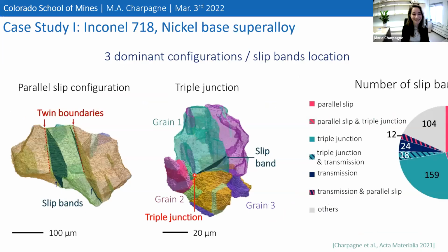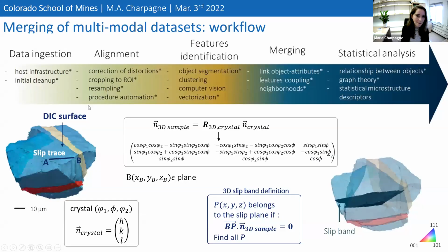Absolutely, yes. Excellent point, and I have a slide for this that I hope will make more sense. This is what I want to show. We have here the whole framework, and as you mentioned, you can see the slip trace on the DIC surface, and you have your grain structure on the surface. But of course, as we ablate the material, there is no sign of any plastic activity underneath this surface that we can tell just by looking at the data.